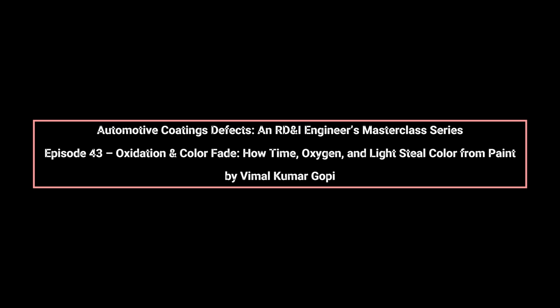From a diagnostic perspective, oxidation and fade present as uniform color loss on exposed panels, stronger color retention under badges or trims, reduced gloss, and chalky residues during washing. Polishing may temporarily restore appearance by removing the oxidized surface layer, but this also thins the clear coat and shortens remaining service life. Corrective strategies focus on durability optimization rather than elimination.